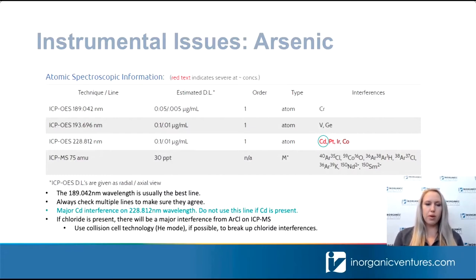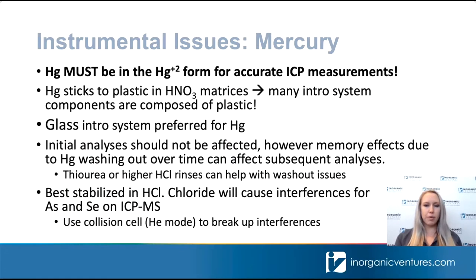Another issue that's very prevalent for arsenic is that it's monoisotopic, so you only have the 75 mass on ICP mass spec, and there's a major chloride interference on this line. So if you have chloride in any of your solutions, it is going to cause issues for analyzing arsenic on ICP mass spec. What we recommend for this is using collision cell technology on your instrument, if that's an option available to you. This is going to be helium mode, and it's going to break up those argon chloride interferences. That brings us to mercury.